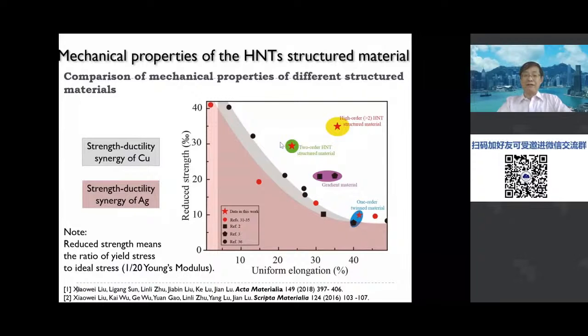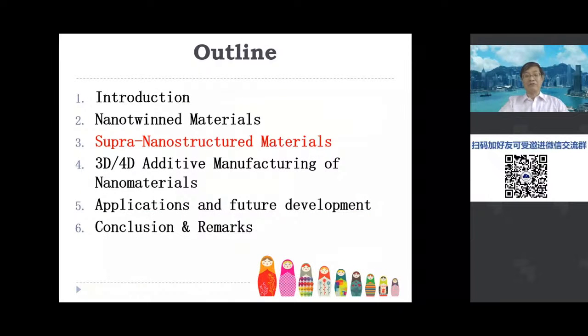Then, if we plot our results on this curve, we can see the higher order twin, higher than second order, gets a much better result than two order nano twin, and also much better results than gradient material. So that means we still have a lot of room to improve our mechanical property in the engineering material. This is achieved on the model material, which is pure silver with a very low stacking fault energy. So today, with high entropy alloy, it's possible to generate more nano twin. So I think it's possible in the high entropy alloy, we can also generate the fifth order nano twin, even higher.